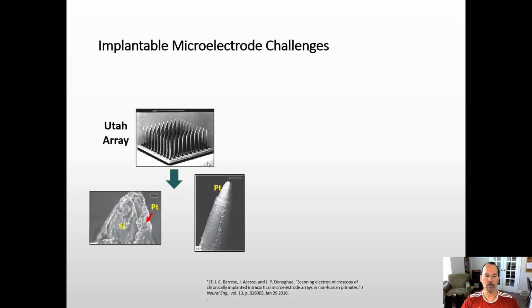So what happens over time? Well, we can have these platinum coated tips, and there's Parylene C coated shanks. We can have the platinum corrode, exposing cytotoxic or toxic silicon to the brain, which causes failure, or we can have a failure in the coating, which does the same thing.